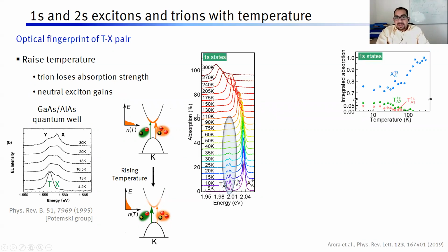And this is exactly what we see for the 1s states in our experiment. We have this low temperature experiment where we have a low temperature spectrum with two Trions and one exciton. We raise the temperature, Trions go away. They wash away, they lose strength. Whereas if you calculate the area under the excitons, you find that their strength rises. The Trions go down and the exciton rises. So this is in line with what was discovered already in 1995.